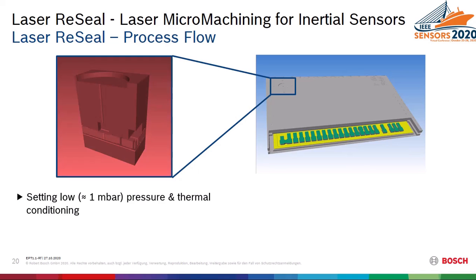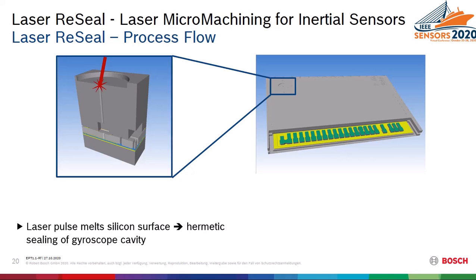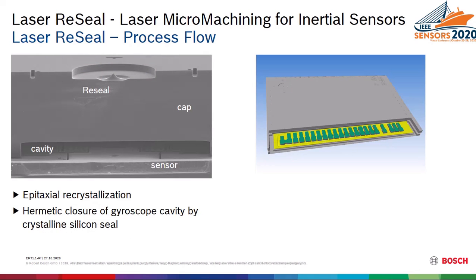Then you will place the whole wafer into a vacuum chamber where you evacuate the gyroscope pressure. You set the right pressure and do some thermal annealing, and then with an infrared microsecond laser pulse you can locally melt the silicon around the vent hole, and the molten silicon upon cooling down will seal your vent hole. And it really looks like this.